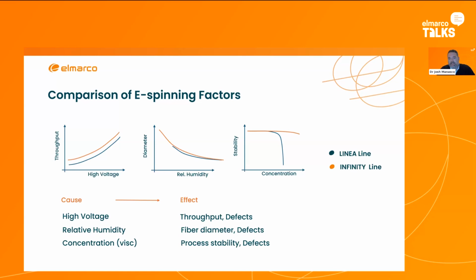Our goal was to reduce the defects. But in this case, we've also seen that we get benefits in throughput and bigger flexibility in our ability to form fibers at different sizes with different materials. It also is another added benefit that we found that some materials that don't spin at all on the Linea machine now are able to be spun and produce higher quality materials on the Infinity line, which is another added